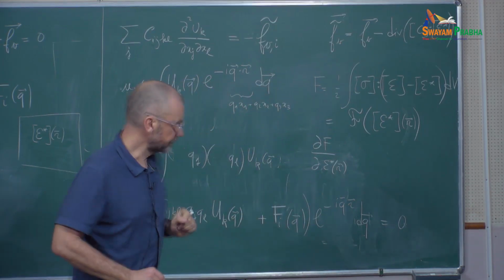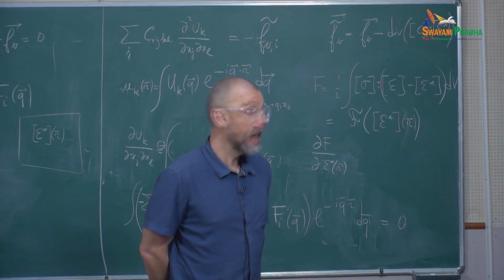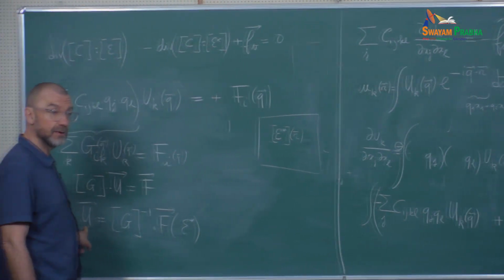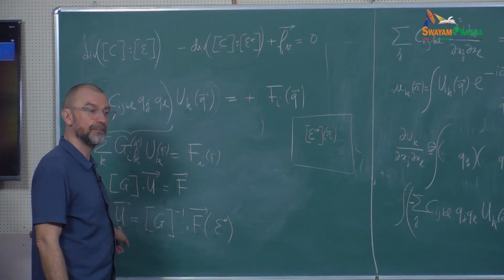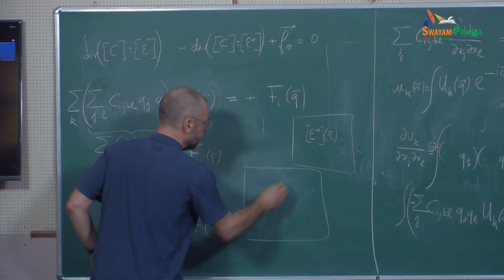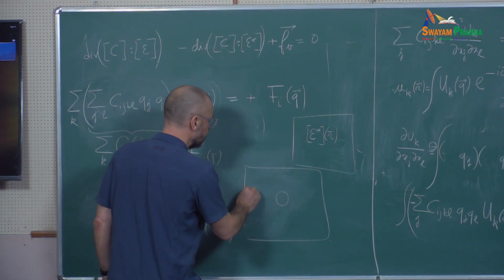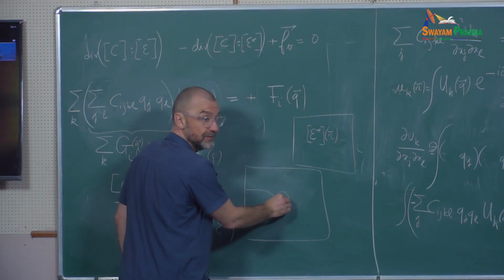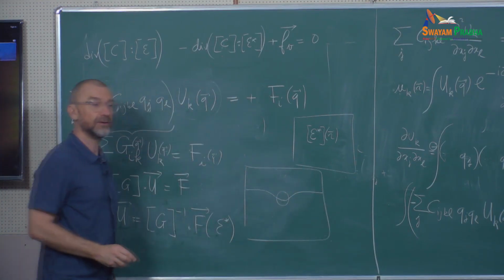So now, we are assuming that only the precipitate is getting strained and not the matrix. So in the end, when you solve for the elasticity, the displacement will be non-zero inside the precipitate, but also outside the precipitate. And it will vary. If I have a big enough cell and I have a precipitate, the displacement will be zero far away, and then it will go down. It will be close to A minus A prime inside, and then it will go back further away.